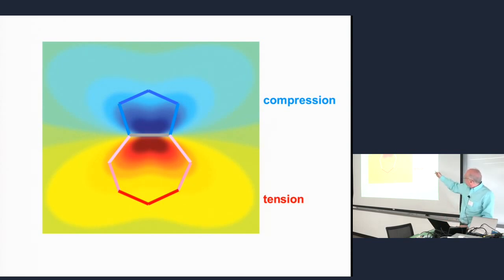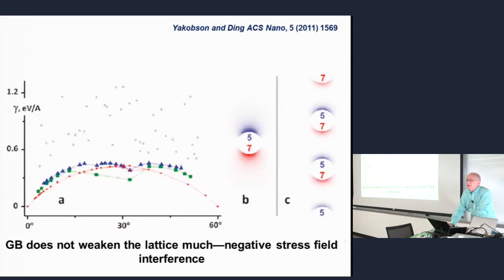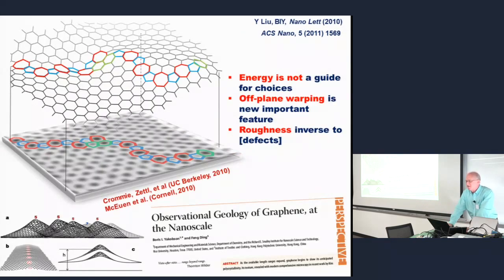That's how strain stress looks like. You have tension here, compression here. If you compute it using elasticity theory, it gives you a very good idea that these bonds are under tension, these bonds are under compression. So you can know which one will first break. This explains that they reduce strength generally. You can go further, and you can understand that if you have many of them, actually strength can recover and become a little bit stronger, although you have more defects. But the mechanism behind it is extremely simple. They just cancel each other, because if you have stress distribution like this, plus minus on opposite sides, and then you have an array of them, then they cancel each other in the middle. You have partial compensation. That's why you have more defects, but material looks stronger. That's very simple. You don't need to do any sophisticated computations.